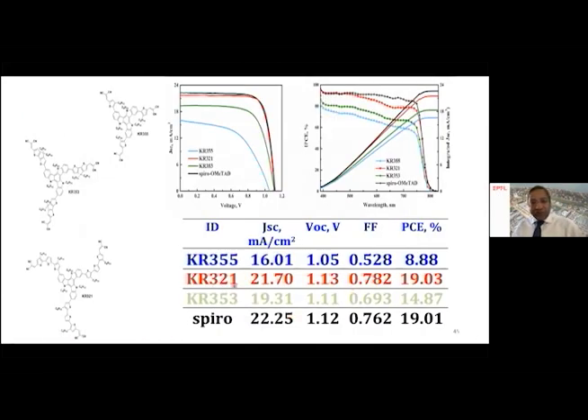And they get the same efficiency as spiro-OMeTAD. So look at the data. For spiro-OMeTAD, the standard efficiency is 19%. Spiro-OMeTAD is doped with cobalt, lithium TFSI, tertiary butylpyridine. However, KR321, which has three thiophene groups, used directly from the lab onto the cell, still gives 19% efficiency. So this is the first time we came up with a dopant-free hole transporting material reaching the same efficiency as doped hole transporting material. And in between, the two-thiophene one gives 15%, and the one-thiophene one gives an even lower efficiency.